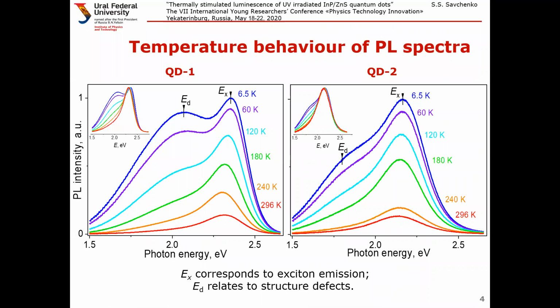At room temperature, the samples have asymmetric emission bands. Upon temperature decreasing, intensity grows and spectral shoulders appear in the low energy region. For QD1, this feature turns to local maximum at low temperature. The high and low energy bands are assumed to originate from exciton and defect-related states correspondingly.